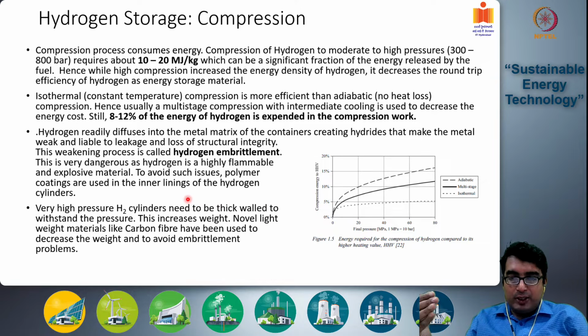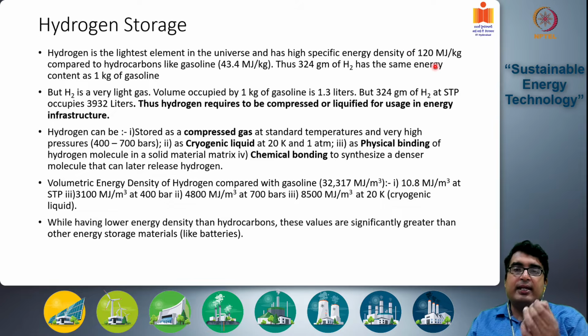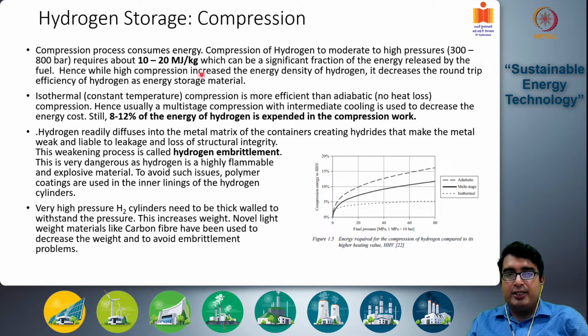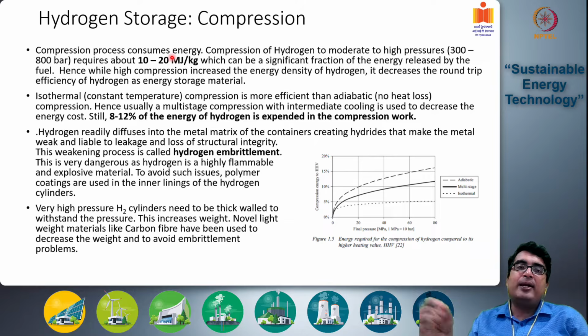However, when you compress hydrogen, you need energy to compress it to such high pressures. So hydrogen compression in general requires around 10 to 20 megajoules per kg, which can be a significant fraction of the energy released by the fuel. The total energy density of hydrogen is 120 megajoules per kg, and if you are compressing it to very high pressures, you can expend up to 20 megajoules per kg. So around 1/6 of the total energy content of hydrogen is expended through the compression process alone. If it's at lower compression, the energy required will be lower, but then also the energy density will be lower as well.